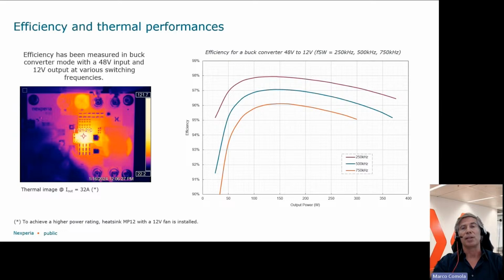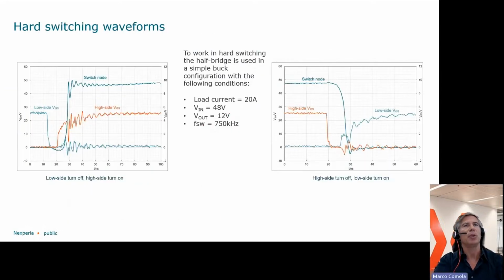Higher efficiency is translated, of course, into lower temperature. You can see that at high load, at full load, let me say 32 amps, the temperature of the GaN device is close to 120 degrees. And of course, in the application we use a heat sink and a fan, a 12 volt fan. And let me go on.